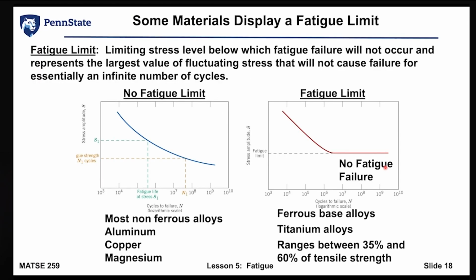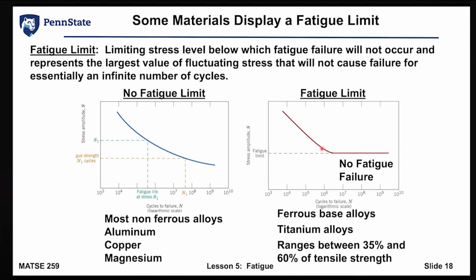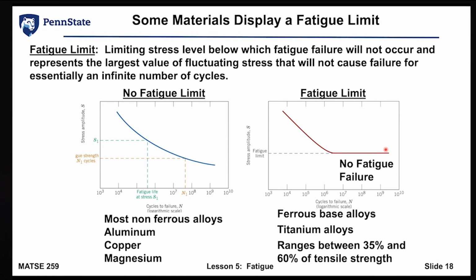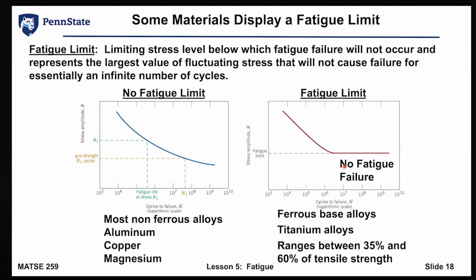Some materials, though, provide us with something really interesting. Rather than continuing down into infinity, almost to zero, they will reach a point where, after a certain stress level, it goes no lower, and they don't fail by fatigue. What we typically call these in testing is a run out. So we'll test something to 10 to the 7th, 10 to the 8th cycles, and if it didn't fail at that point, we'll say it's a run out. This is how we start to define fatigue limits for a certain number of stress amplitudes or cycles to failure. So we can limit the stress level.